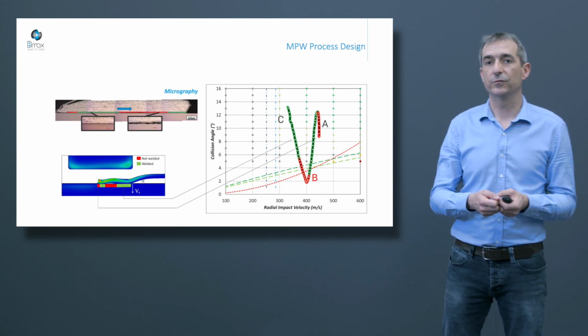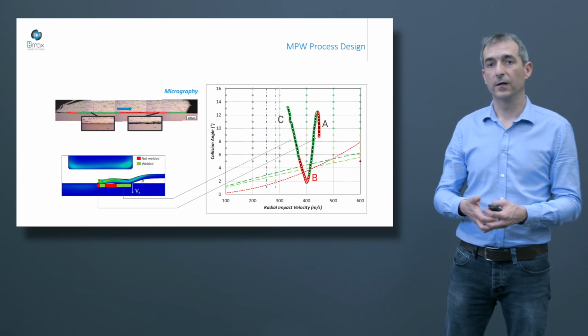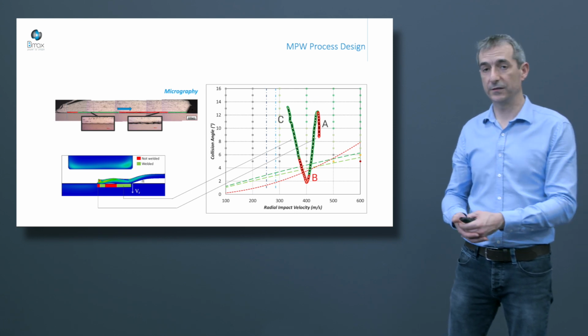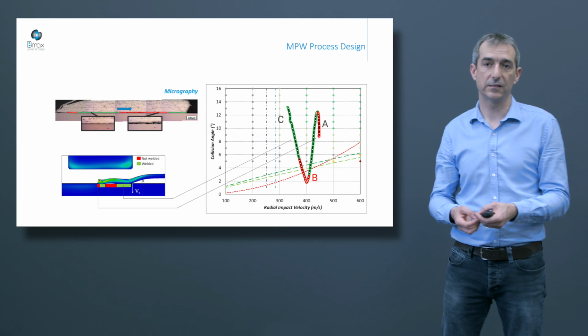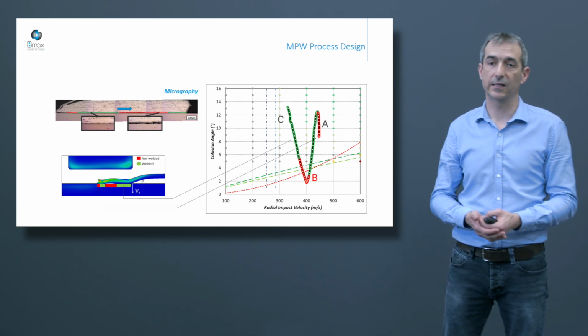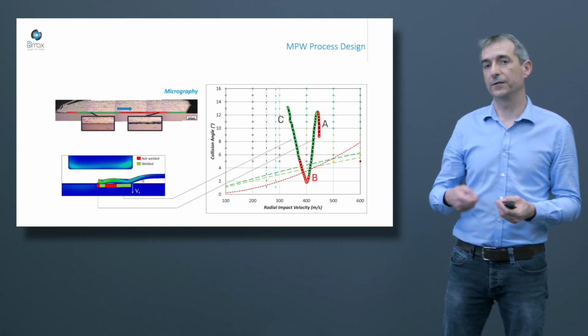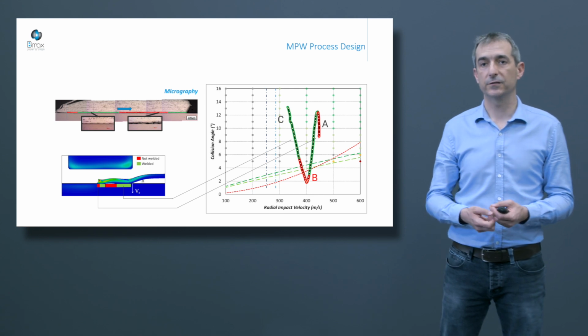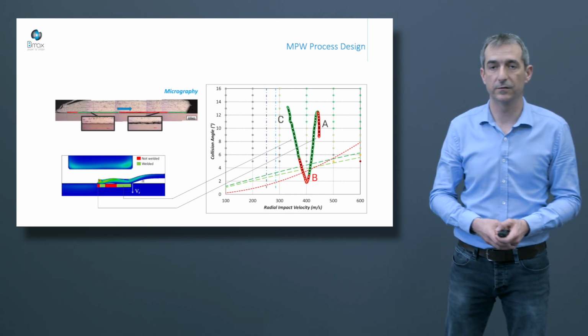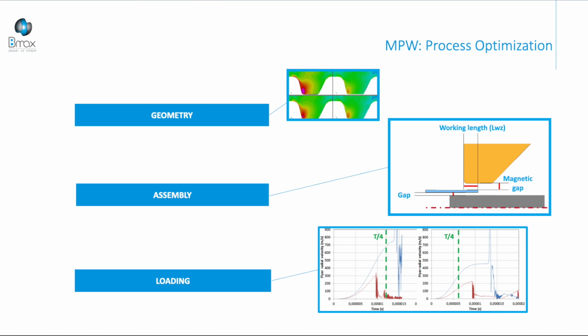After, in the process, we have a decrease of the angle, and we go out of the welding window. We are at point B, and at this point, we have no welding, as expected. After, the angle at the end of the process increases again, and we are at point C. We have a good weld at this point. So by simulation, we can optimize any parameters like geometry, assemblies, and loadings to enhance this result.